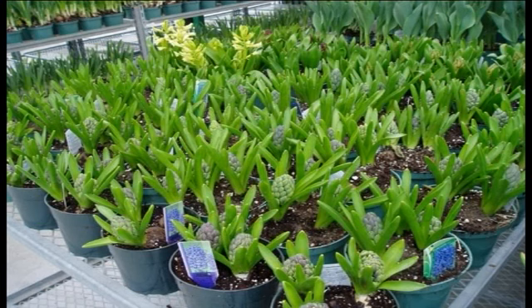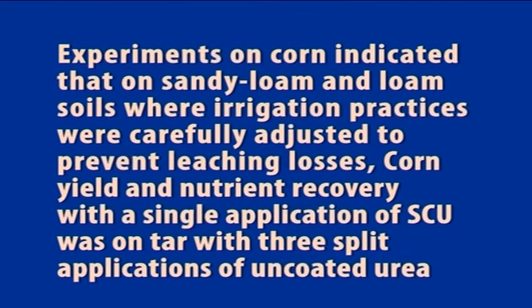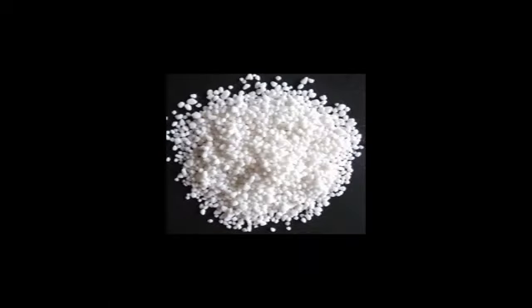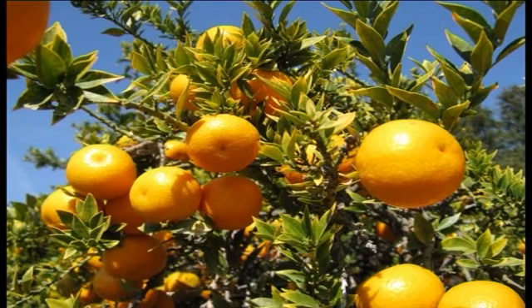Sulfur coated urea is also reported to be an excellent nutrient source for ornamental plants in pots. Experiments on corn indicated that on sandy loam and loam soils where irrigation practices were carefully adjusted to prevent leaching losses, corn yield and nutrient recovery with a single application of sulfur coated urea was on par with 3 split applications of uncoated urea. Single application of sulfur coated urea resulted in more yield and more evenly distributed forage and protein than due to 3 split applications of ammonium nitrate and nitric phosphate. Observations were similar in crops like sugarcane, citrus and rice.